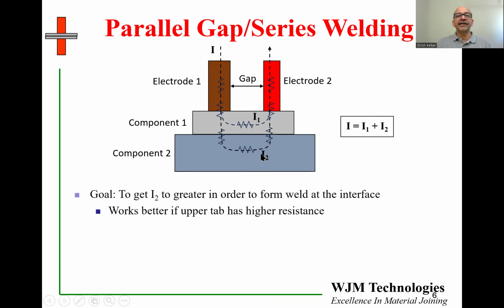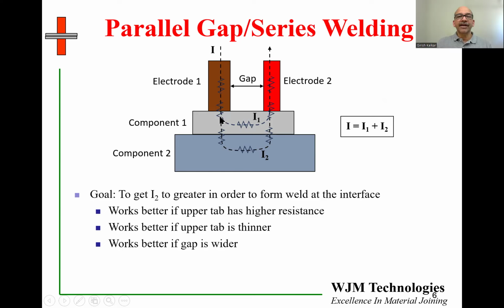One of the ways to increase I2 is to increase the resistance of the top tab. If the top tab has high resistance, then the current would try to go down into the bottom component and then come back up. Another way is to make the top component as thin as possible. If the top component is thin, then again, it will be easier for the current to go down and come back up. Another option is to increase the gap between the 2 electrodes. The wider the gap, the more likely that the current will go down and come back up rather than going through the top tab.